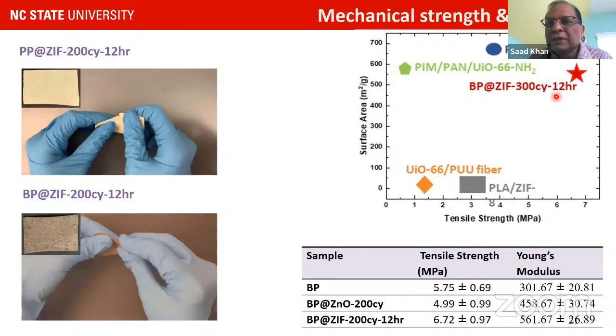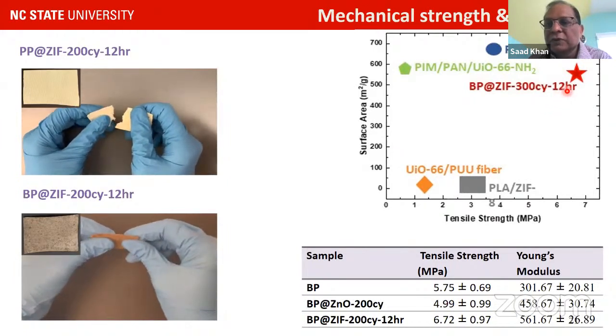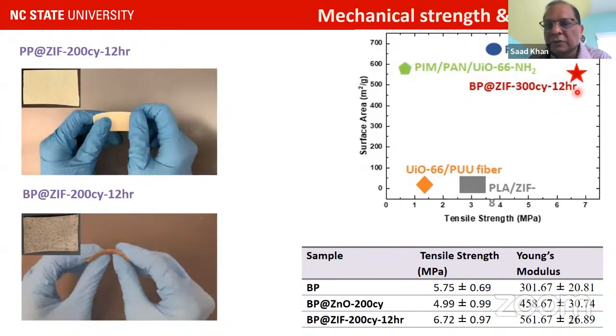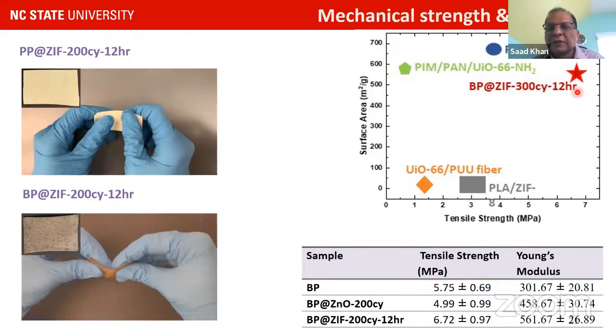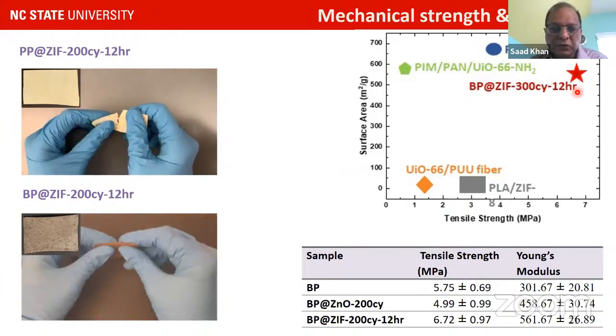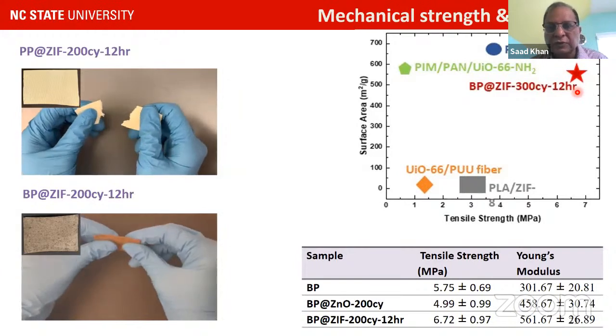And perhaps one interesting thing is we've tried to show here surface area versus tensile strength. And what we find is that we get the best of both worlds when we use banana paper MOF. We get good tensile strength. We also have good surface area. So it's a very nice compromise when you're trying to use these features as well.